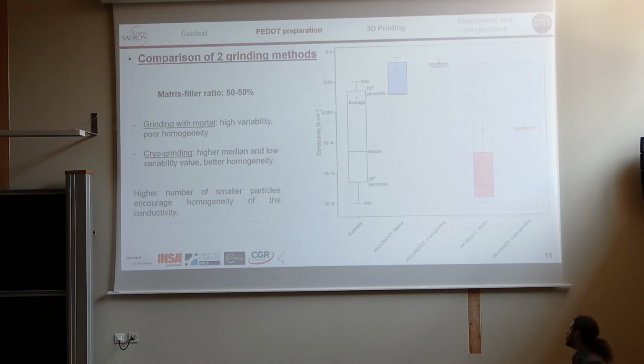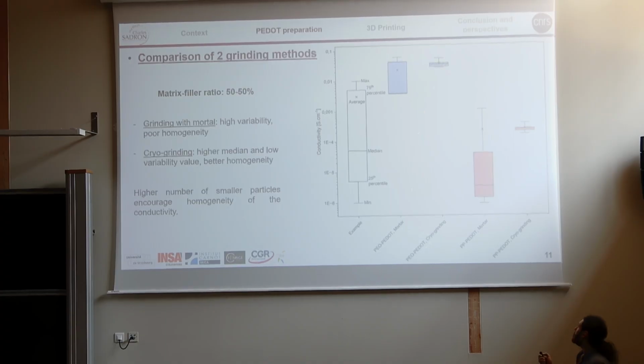And the results are also observed in the conductivity of the composite, because as you can see here, when using the cryo grinder, you have a median value of the conductivity that's much higher than with the mortar, but also a much reduced variation of the values, which means that we have a much more homogeneous material. We don't have big chunks of PEDOT at some point that will create depleted regions elsewhere. So we have something very homogeneous.